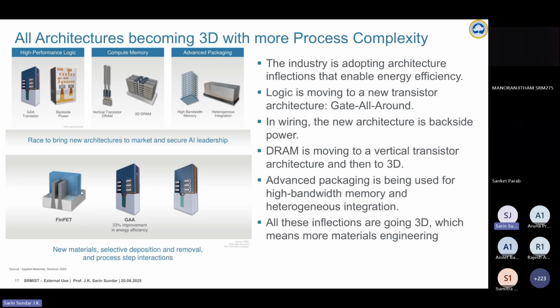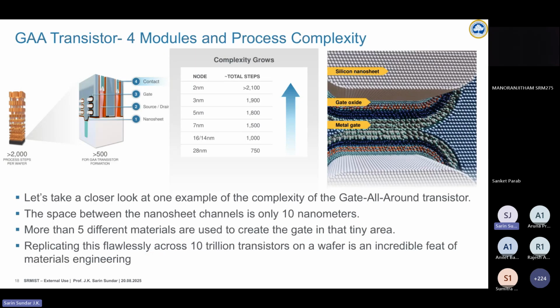And also, on the logic side, I will show you a short video of gate-all-around, mainly to show different kinds of processes, both the manufacturing processes and the defect inspection processes that we do. Before we go there, you can look at the number of steps. Steps here means the number of manufacturing process steps, usually your CVD deposition step, your material removal etch step, your material modification step, or your inspection step. The 28 nanometer node typically had about 750 process steps. Today, we have more than 2,100 process steps for the 2 nanometer gate-all-around.